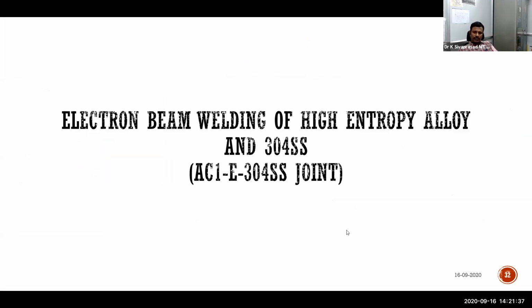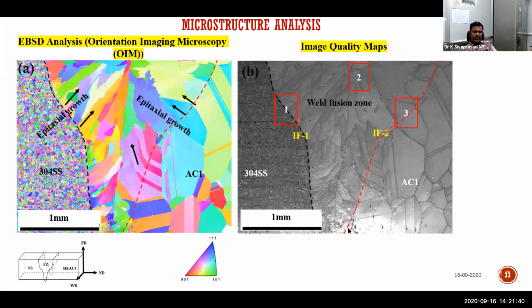Then electron beam welding of these systems when we started doing. Earlier one was TIG welding, now this is electron beam welding. When we have done electron beam welding, here also you can see on the high entropy alloy side epitaxial growth, orientation relation one can clearly see here. Here you can see more precisely the orientation relation, whereas such orientation relation is not followed here. Further, the system was so fine that we could not even trace out whether type 2 boundaries are formed here or not. So that is the beauty associated with the system. The type 2 boundaries are not formed.